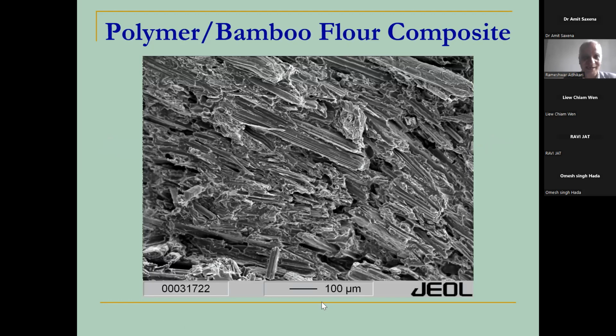So you can see that. You can see only bamboo actually. So this composite was some 40% bamboo flour and some 60% biodegradable composite. In this case, what you see here, these layered structures, this layered architecture is of course bamboo, and the other, which is merely acting as a cementing material for this composite, is the polymer.